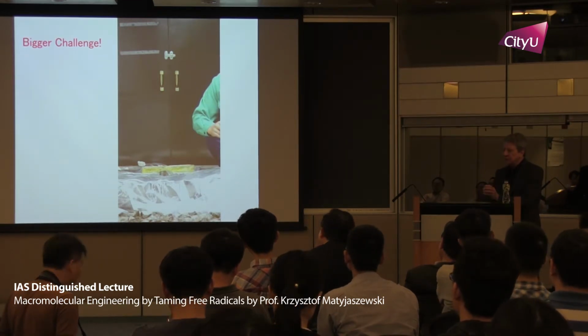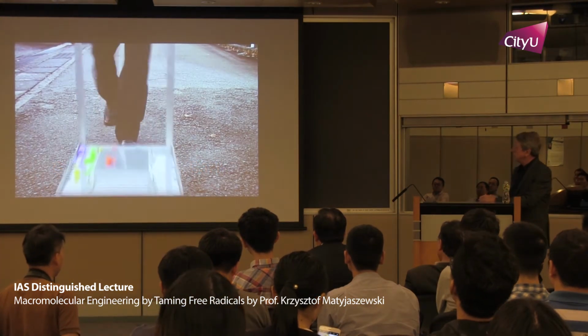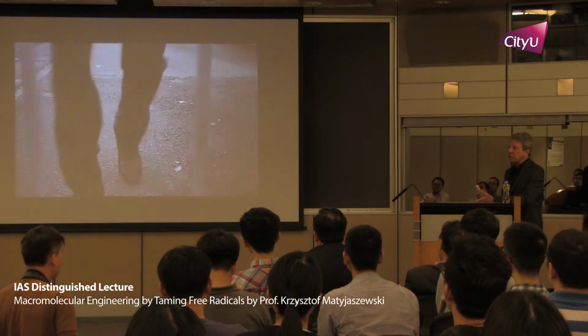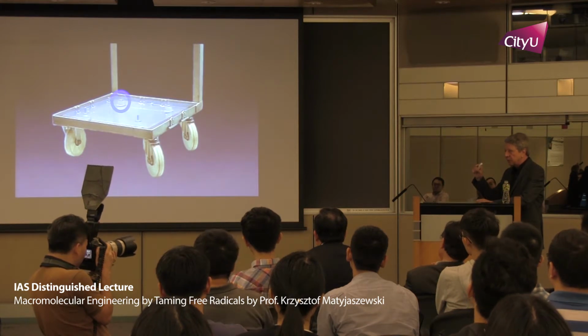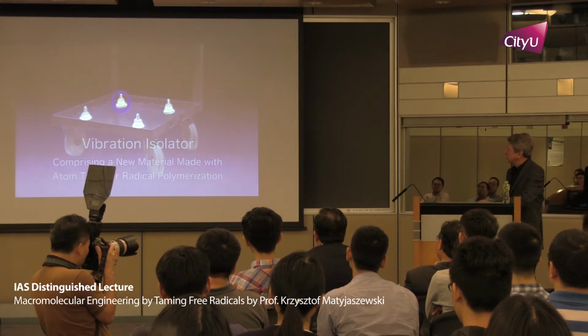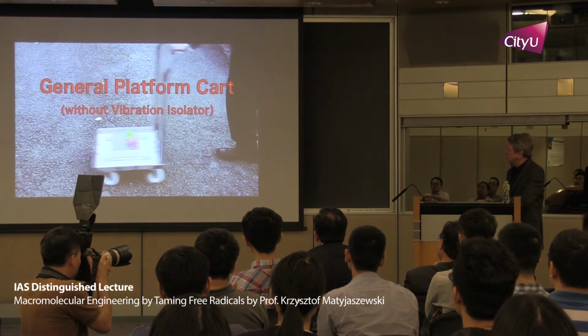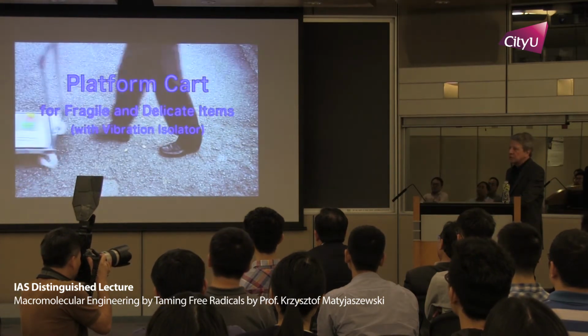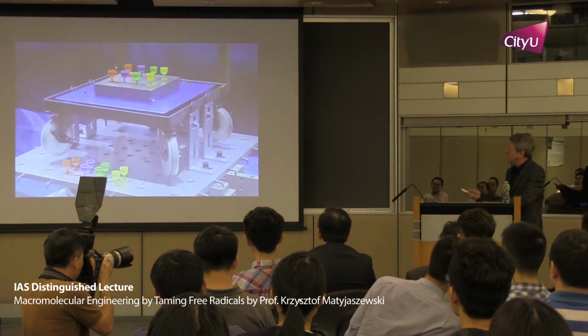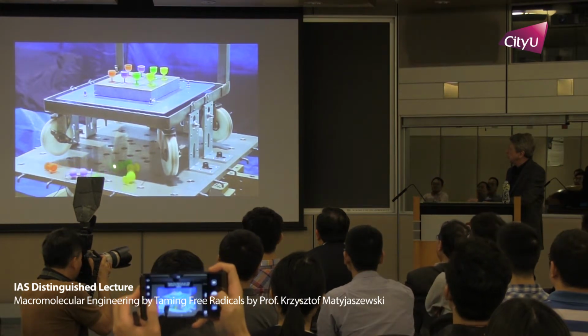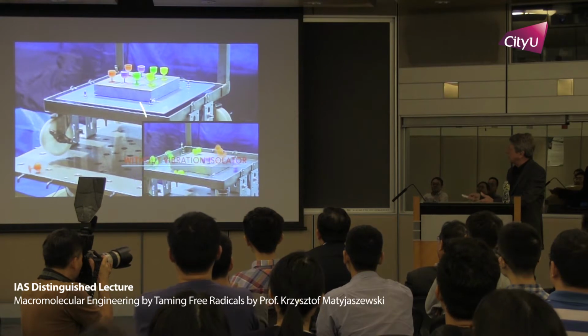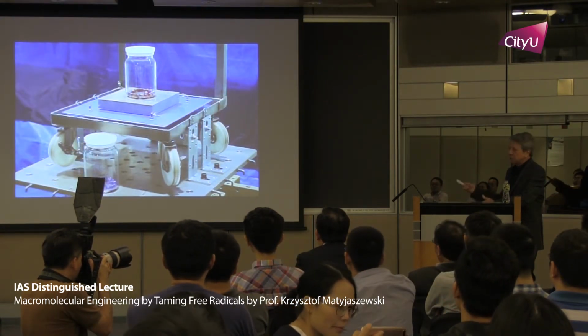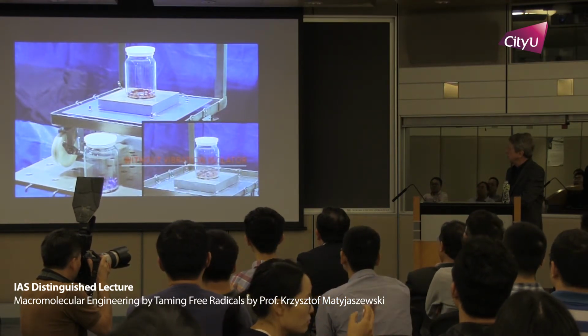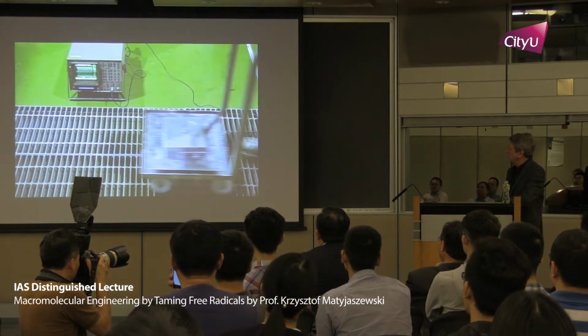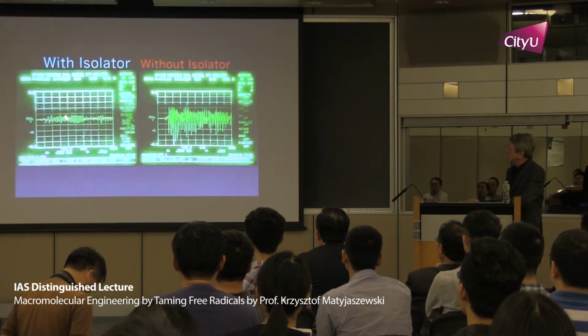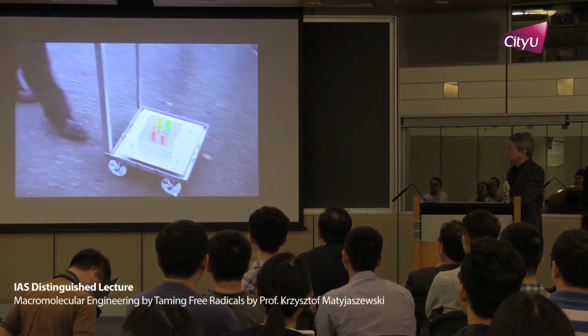So they recently developed a very interesting material which can be used for the transportation of fragile objects. This is with very small vibration isolators prepared by atom transfer radical polymerization, and it's also acting as a shock absorber. This is without, and you could see how it works with this isolator. You can quantify that also and look at the mechanical shaker. This is with, this is without, and if you look at more or less the same time, it's a quite big difference. With steel bearings, it's more or less the same story, and you could see here with isolator and without isolator. So the sample is dramatically different.